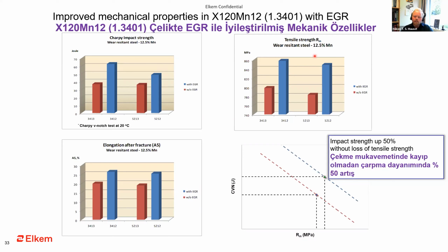When we look at the tensile strength, we see that without EGR, we are at 780, 800 megapascals. But with EGR, we are more up at 840 to 860 megapascals. And we also see that the elongation after fracture, the A5, increases as well. We're typically at around 20% elongation without EGR, and at 25% with EGR. So we see here the impact strength is up 50% without any loss of tensile strength.